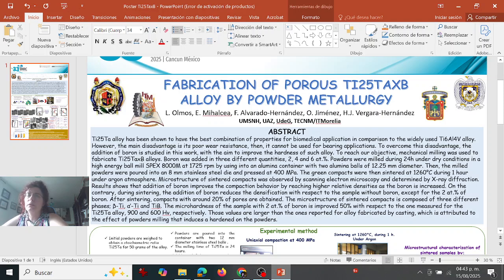Well, after sintering, compacts with around 20% of pores were obtained, and the microstructure of the sintered compact was composed of 3 different phases. So we observe that we have beta titanium, alpha titanium, and also we have titanium boron.